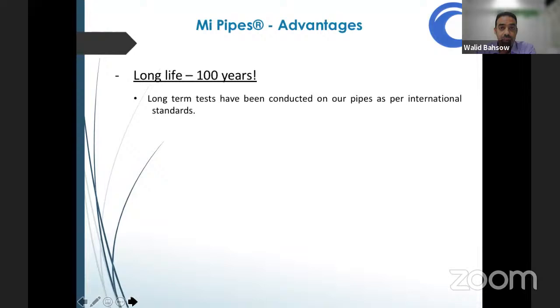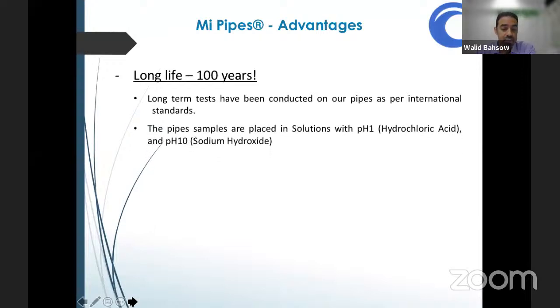So first, you have the long life in terms of the advantages. You have the long life. They've been designed for 100 years. So the international standards require that the pipe samples are placed in solutions of pH 1, hydrochloric acid, and pH 10 for sodium hydroxide. And these samples would have to be kept under load for a period of 10,000 hours. That's around 14 months. And that is only the testing period. So you'll have, of course, a setup period before that.